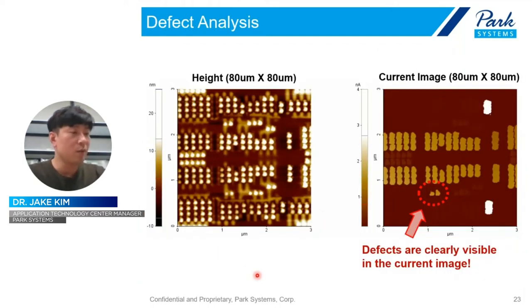And here, let me show you one interesting application of conductive AFM. In the device field or the semiconductor field, connection or defect investigation is quite important. It's very important, but not easy work. But using conductive AFM, we can simply monitor those kinds of defects. Of course, from the optical microscope or EM, like SEM or TEM images, even the AFM height image like this, we cannot recognize the defect. But here, in this current image, the conductive AFM image, it is very easy to check that.